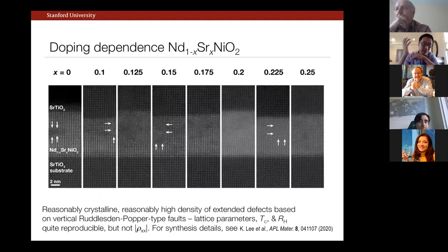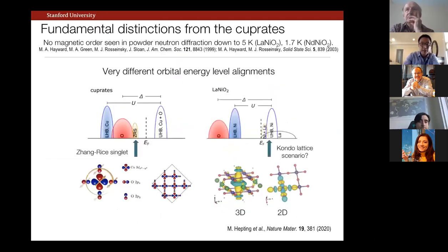At least the first work I'm aware of in the field from a TEM point of view was in this paper by Beatrice. We see very similar things. So what we worry about or suspect, which is a little bit discussed in this paper, is that whatever cation configuration we have, our low temperature reduction doesn't do much to it. So whatever the perfection or imperfection in the perovskite phase is basically mirrored into the infinite layer phase.